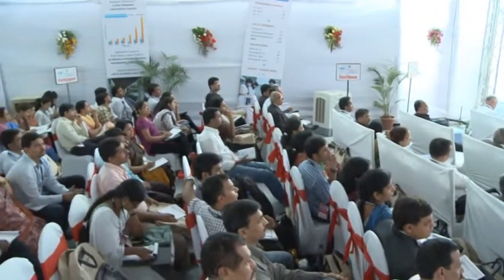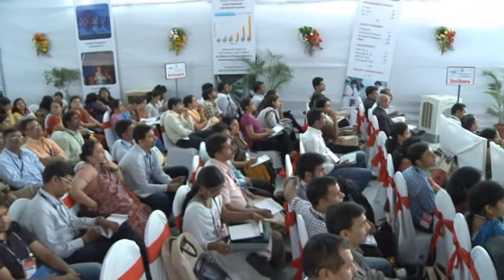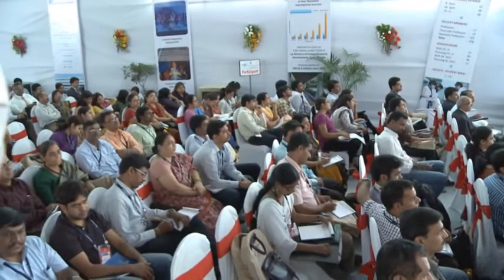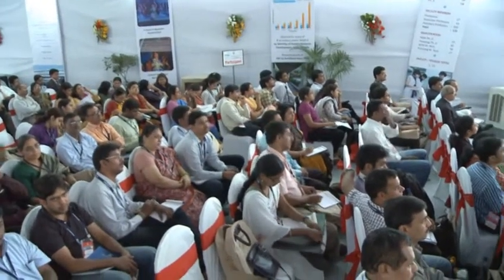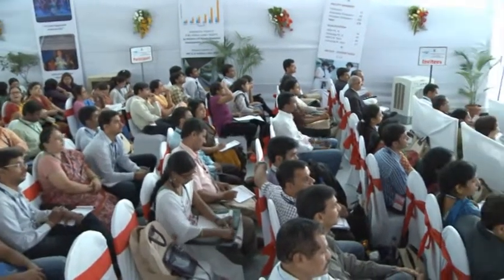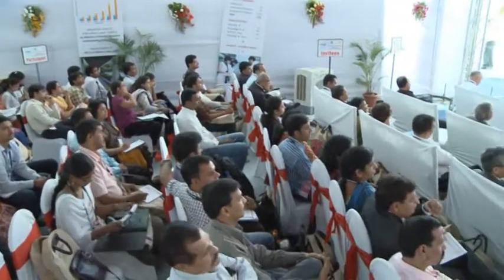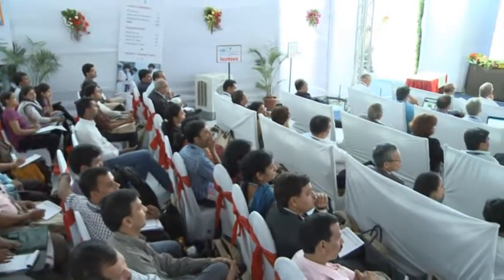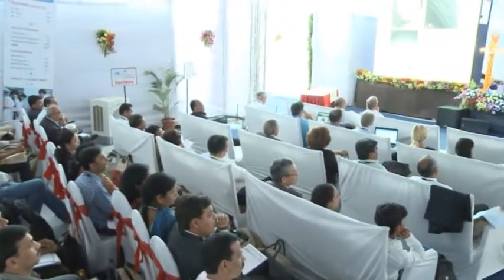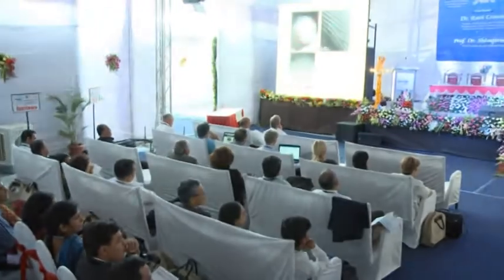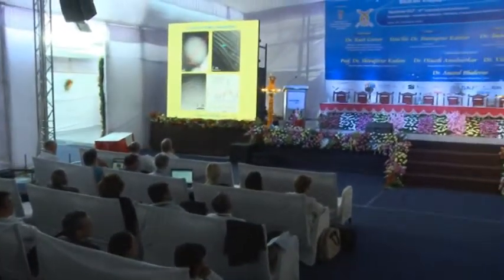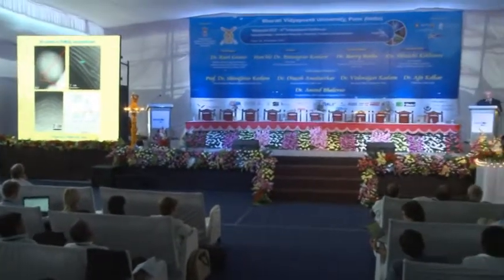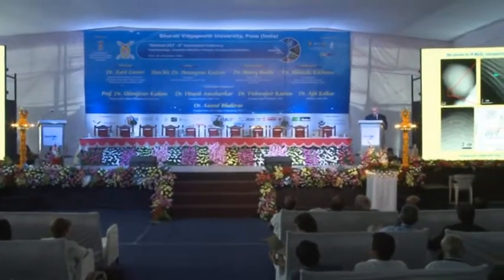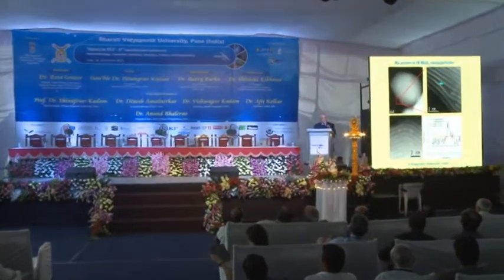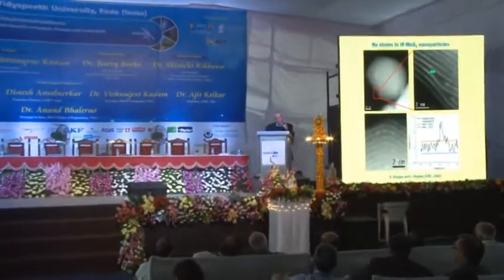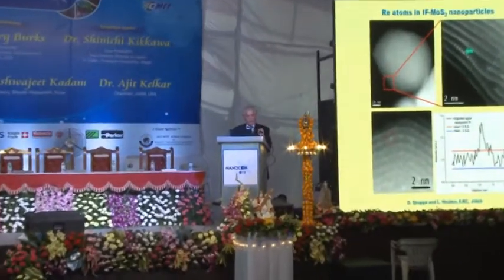When you substitute rhenium into the lattice of the nanoparticles as shown here, you see a single rhenium atom in the lattice of the molybdenum disulfide Fullerene-like nanoparticles. This picture was taken by a Titan microscope in Jülich by D. Stroppa and L. Houben, 2 collaborators in a joint ERC project, in the research center in Jülich. And so we learned how to dope. Each nanoparticle has about 30 to 50 atoms of rhenium.